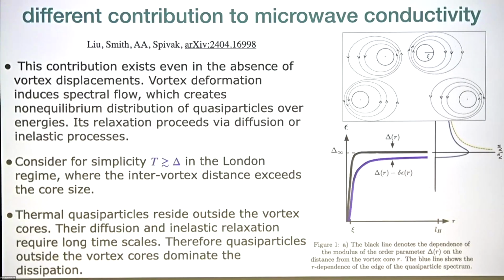And so pictorially, what I will discuss is a relatively high temperature regime, where temperature is of the order of or greater than delta. Then the quasi-particles live not only inside the cores, but also everywhere in the sample. And also I will stick to the London regime, where the intervortex distance is greater than the core size. Then roughly speaking, the picture looks like this, that the order parameter is healed quickly from 0 to its bulk value over length scales of the order of the coherence length.